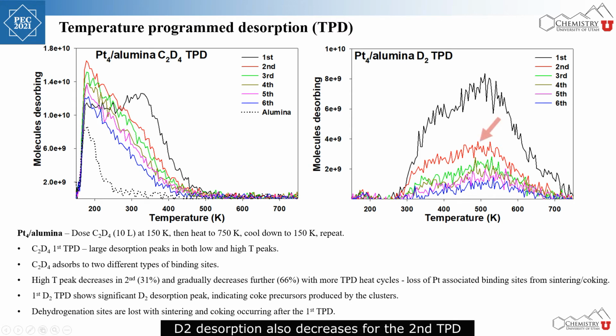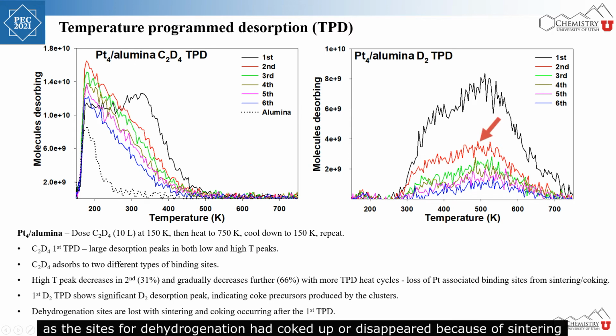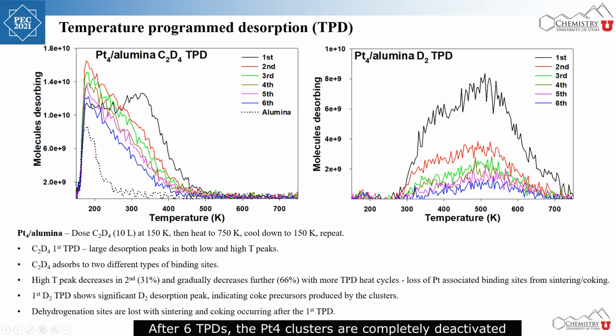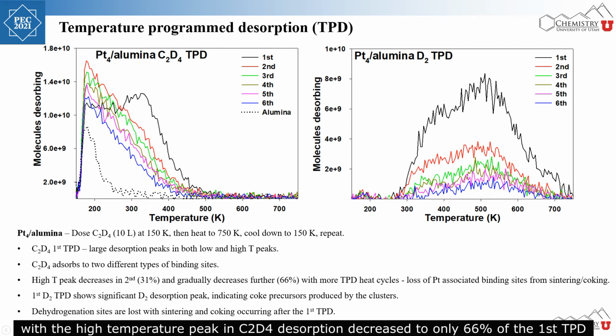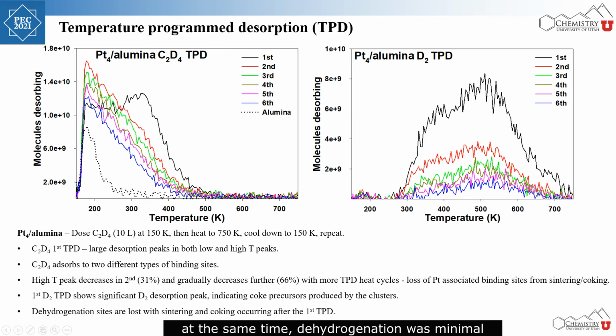D2 desorption also decreases for the second TPD as the sites for dehydrogenation had coked up or disappeared because of sintering. After 6 TPDs, the platinum-4 clusters are completely deactivated, with the high temperature peak in C2D4 desorption decreased to 66% of the first TPD. At the same time, dehydrogenation was minimal. The TPD experiment of platinum-4 alumina tells us the platinum-4 clusters are easily deactivated by coking and sintering.